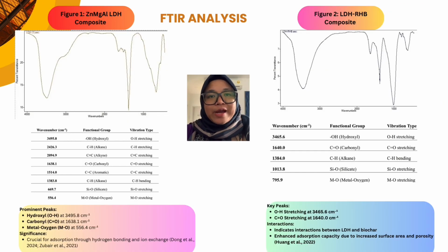Now, let us look at the FTIR analysis of the LDH and LDH with rice husk biochar composite. In the zinc, magnesium, aluminium LDH composite, we observe key functional groups such as hydroxyl at 3495.8, the carbonyl at 1638.1, and the metal oxygen bonds at 556.4. These groups are crucial for the adsorption process. And for the LDH with rice-husk biochar composite, similar functional groups were present with slight shifts in wave numbers. The hydroxyl group was observed at 3,465.6 and the carbonyl group at 1,640. The presence of the silicate group at 1,013.8 from biochar indicates enhanced surface area and porosity, which are beneficial for adsorption.